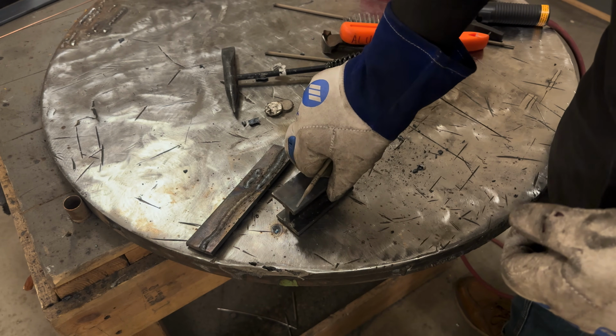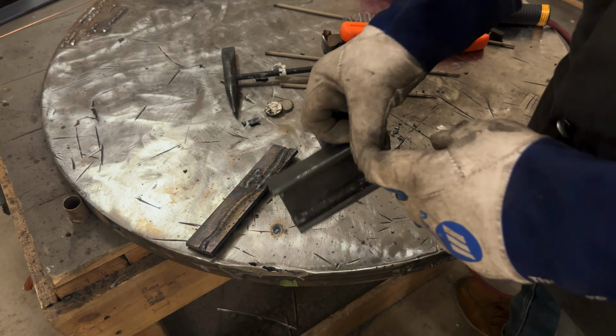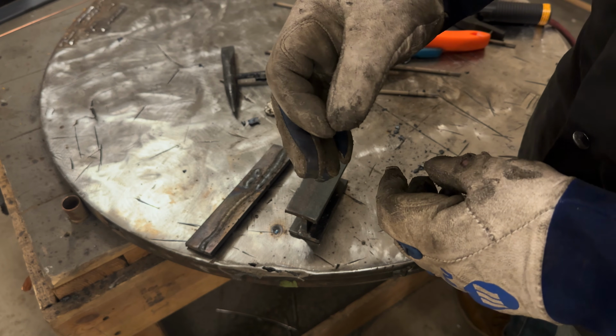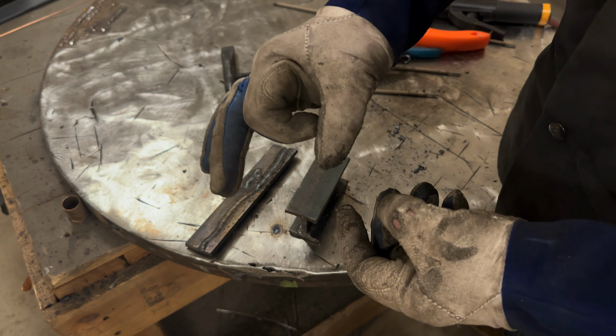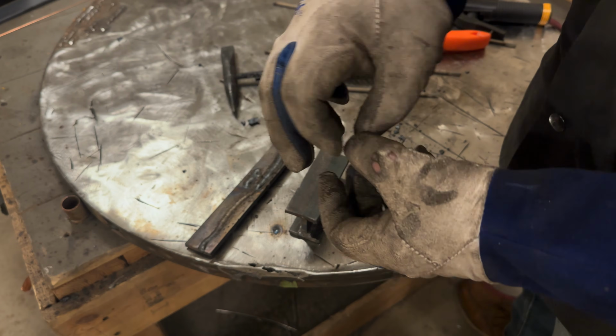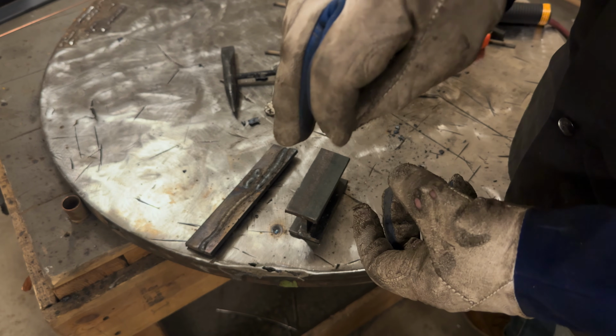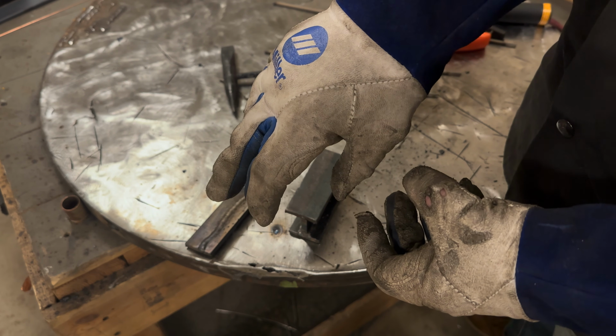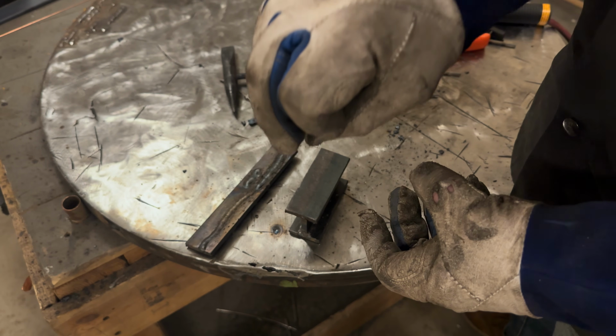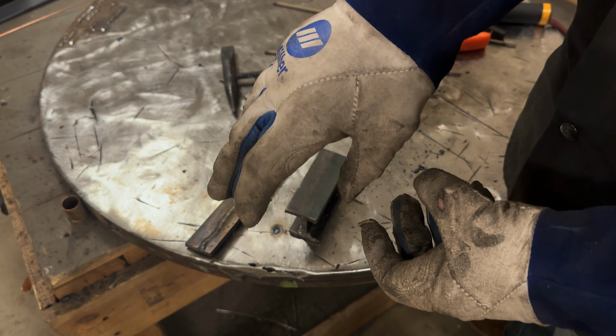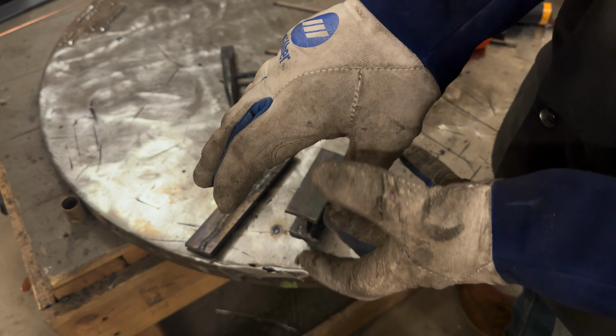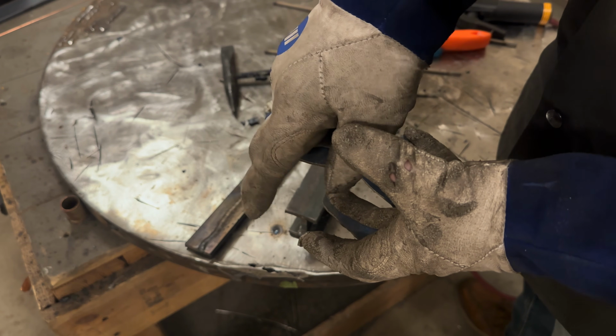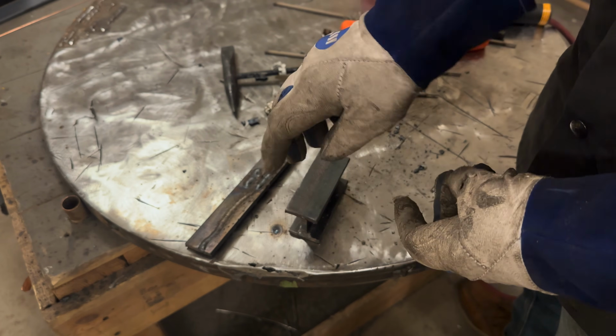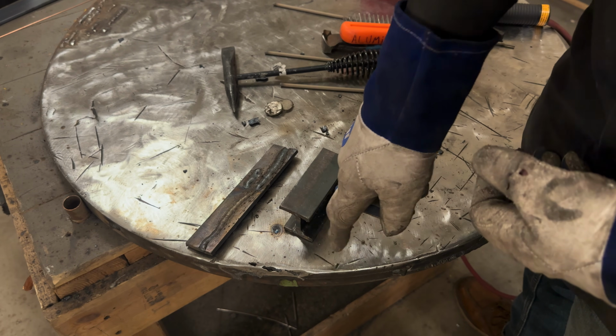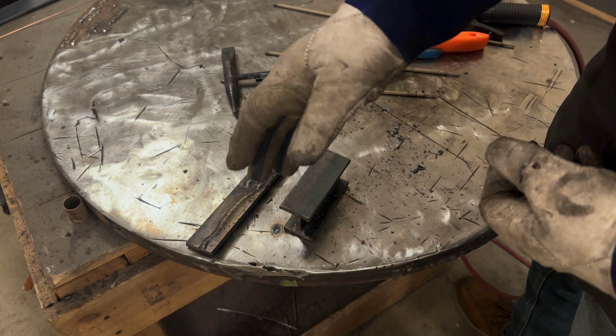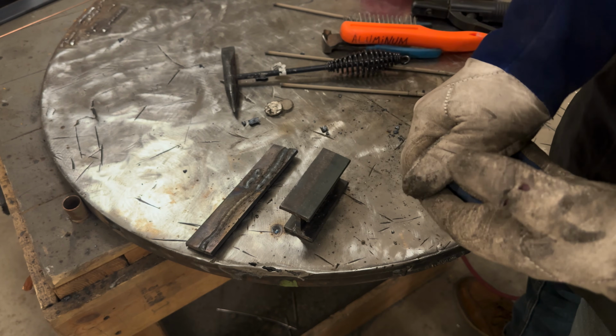And that's why I find with AC TIG on thicker material, and especially on inside corners, that putting a ball on the end of your tungsten actually helps, because it gives a bigger, more solid target for those electrons to hit. If you weld enough with it, you see that your arc cone, which is just brightness, you don't see electrons, it's almost like a plasma, per se, is more consistent above 120 amps with a ball on it and less likely to wander than with a sharpened tip. You could get arc wandering, and like I said, for the same reason as with stick, you might cut off your ground path. So ground does play a role in TIG with keeping the arc where you want it with AC.